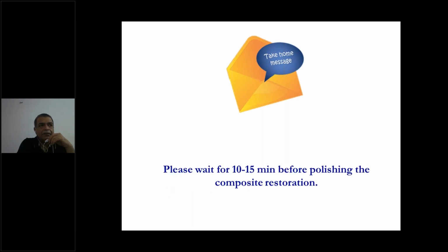This is another very important thing. As soon as the composite restoration is over, we start polishing it. Please understand, when you have given the last shot of curing light, the curing light time is over, but the polymerization is still happening inside. It needs to reach its final threshold before you start polishing it. So it is always recommended, once you are finished with your composite restoration, to ask the patient to sit for 10 to 15 minutes before you start polishing.